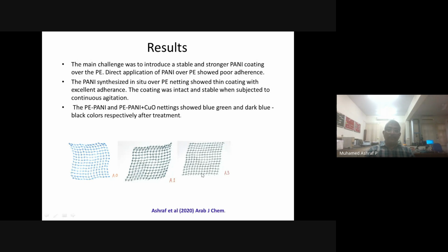Then another thing is we have to add a biocide. Polyaniline is not a biocide; we have only made a polar surface over that. Then we immersed this polyaniline-coated net in a nano copper oxide solution of 0.02%. I'm talking about a 0.02% solution. And we found that the nano copper oxide was uniformly coated over the polyaniline-coated aquaculture cage nets.